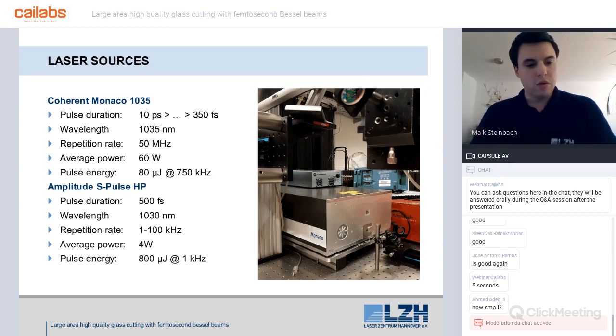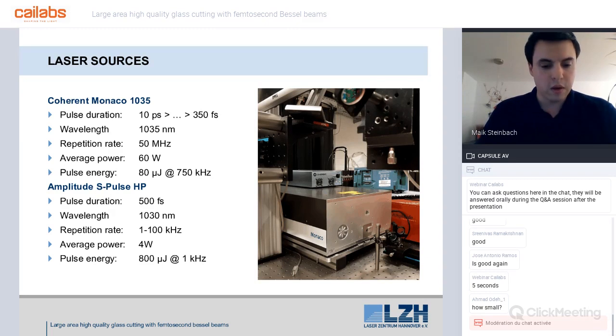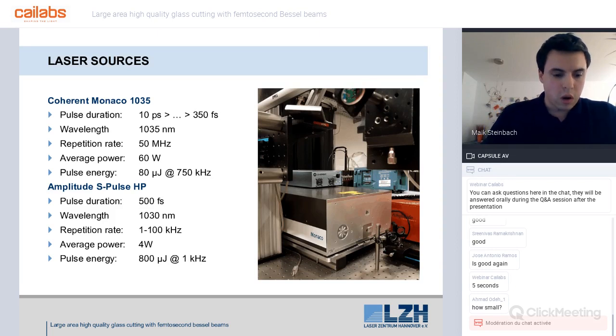The second laser is an Amplitude S-Pulse HP, with a pulse duration of 500 femtoseconds. Wavelength is 1030 nanometers. Repetition rate ranges between 1 kilohertz and 100 kilohertz with an average power of 4 watts. The maximum pulse energy of the S-Pulse is 800 microjoules at 1 kilohertz. With these two systems, we can test a large variety of laser parameters and develop laser processes for industrial and scientific applications.